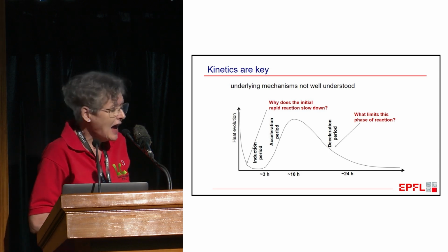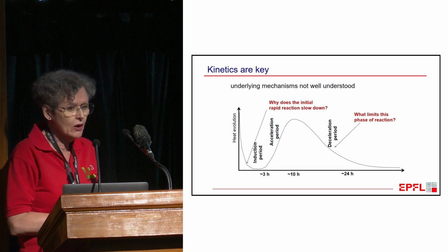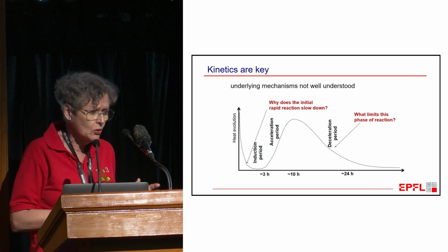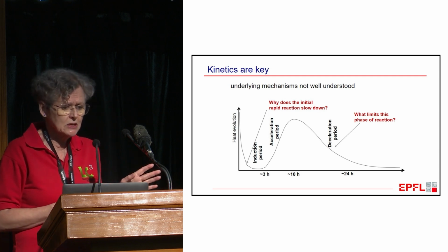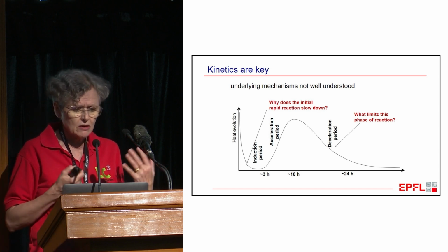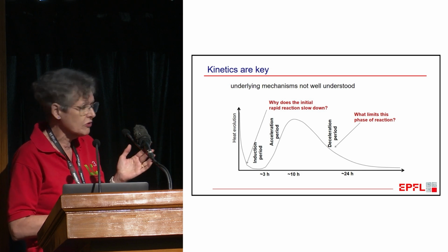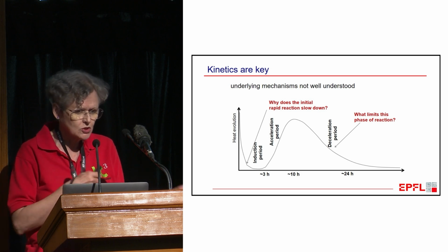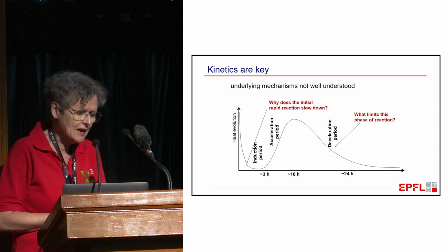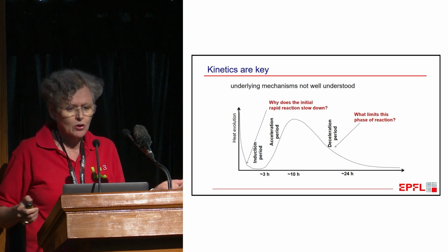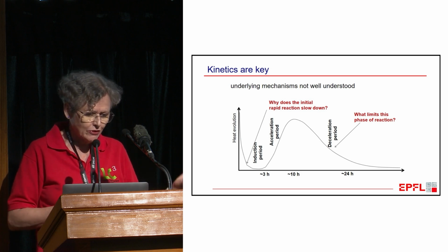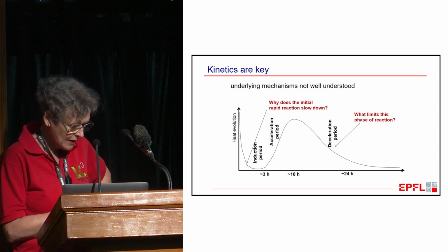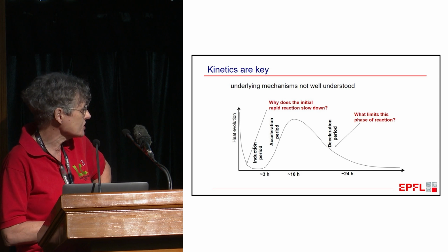Okay, we're back. And then we have a period of slower heat evolution. This is often called the induction period. And from a practical point of view, this is extremely important because this means you have the time: you make your concrete in a ready mix plant, you then have like 2 or 3 hours to transport it to the job site and put it in the forms. And we also have a very well elaborated admixture technology, which means you can prolong this period. If you have some bad traffic, you can prolong this period to make sure that your cement doesn't set too early. But then once you've got it in the forms, the reaction starts to take off again.